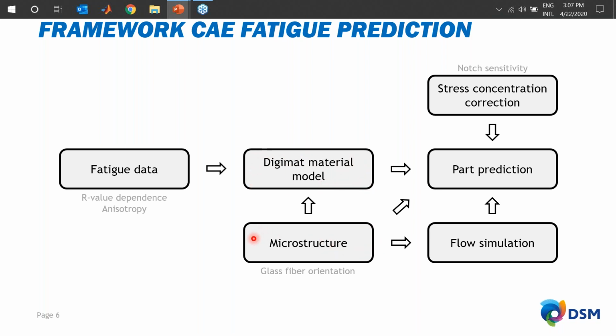So you do CT experiments to also measure the glass fiber orientation that you can use as an input for the DIGIMAT material model. The nice thing is, if you know what the microstructure is that resulted from some kind of injection molding process, you can also use that to tailor the properties of your flow simulation to also enable better fiber orientation predictions when performing a mold flow simulation on your part. And once you know the orientation in your part and you have the material model, you can compute the stresses in a part. If you have the part prediction, then what you will find out is that especially in highly stressed regions, you'll find that there's an effect of stress concentrations which you have to correct. So this notch sensitivity has to be calibrated and also taken into account, as we will demonstrate in a second.